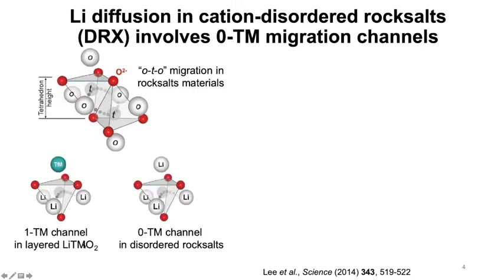In layered rocksalt, the lithium migration mainly happens through this 1TM migration channel, in which the intermediate tetrahedral site is coordinated by one transition metal and three lithium. That's why it's called the 1TM channel. However, in DRX material, this type of 1TM channel is no longer active for lithium transport. Instead, the lithium transport heavily relies on the so-called 0TM channel, in which the intermediate tetrahedral site along the lithium migration pathway is coordinated by zero transition metal. That's why it's called the 0TM channel.